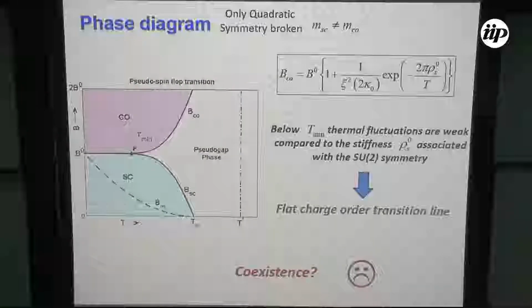So if you look at the functional form of this B_CO, you can see that there is an exponential -1/t dependence. That means it's exponentially flat. And this flatness is not dependent on any parameters, so it's not specific to any fine-tuning of the parameters in the system. So we can reach this flatness, and the extent of flatness is controlled by this parameter, which is the stiffness associated with this symmetry.